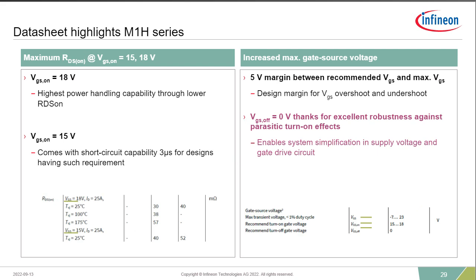I mentioned before about the differences between the M1 and M1H series. And one of the key advantages in the M1H series is that we've implemented the wider VGS specification for the devices. So you can drive the devices at 15 volts and get around 3 microseconds of short circuit capability, or you can increase the VGS specification to 18 volts, lower your RDS(on) specification by between 20 and 25%, but at the same time eliminate your short circuit capability of the device.